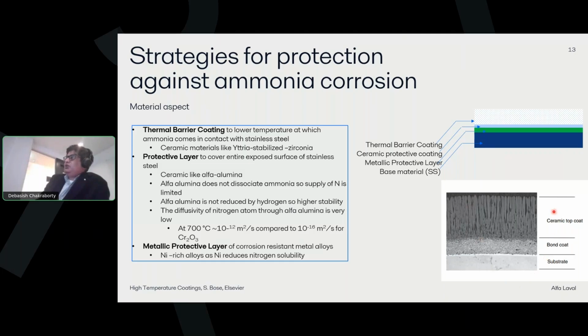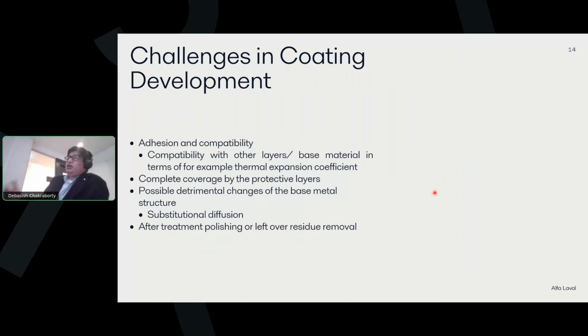So this could be a good protective layer, and depending on your application, you have to choose. And then there are challenges like adhesion and compatibility with other layers and the base material, for example thermal expansion coefficients, because they could be different and things will fall apart. It is also very important that the protective layer covers entirely. If you have just a hairline crack, that will be the point of attack. That's why a multi-layer coating is probably the way to go.